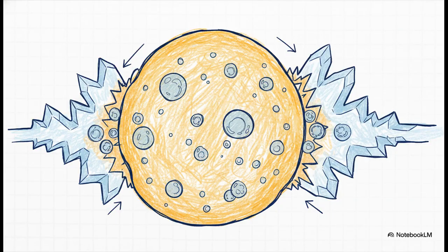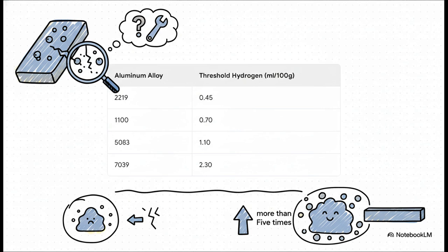So as that molten pool is freezing, it's a mad dash. Liquid metal can hold a ton of dissolved gas, especially hydrogen. But as it starts to solidify, it can't hold as much, so that gas gets squeezed out. If it can't escape to the surface in time, it gets trapped, forming these tiny bubbles or pores inside your weld. And get this: the tolerance for this trapped gas is all over the place depending on the alloy. Just look at this data. The 2219 alloy can barely handle any hydrogen, just 0.45 milliliters. But then you look at 7039, and it can handle more than 5 times that amount before porosity becomes a huge problem. So the material you choose completely changes the rules of the game.